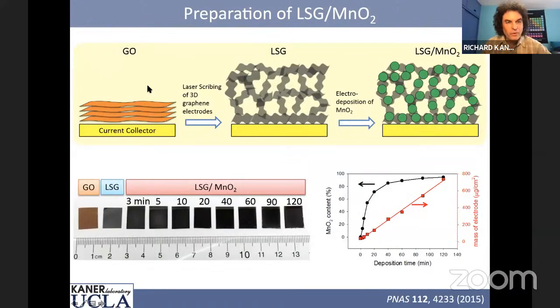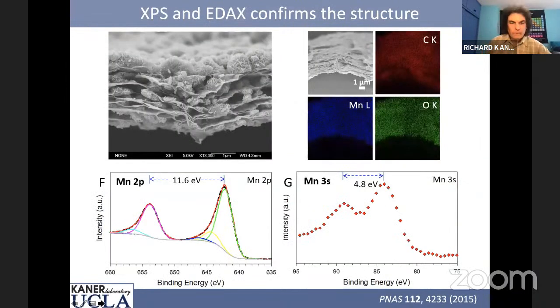And this works quite well. There's many ways to do this. You can do this chemically or electrochemically. And we're basically using our laser scribed graphene as a structure to hold the battery type material. And so we can grow different amounts of manganese dioxide inside this, and we can look at what the results are. So here's what it looks like under a microscope. You can see the layered structure of the chemically reduced or chemically converted graphene oxide with a laser.